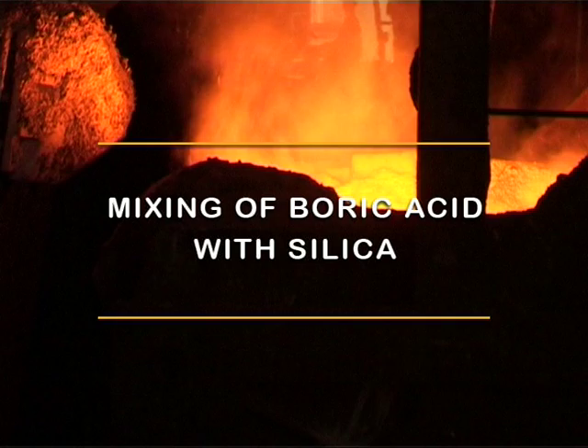Mixing of boric acid with silica. Can you comment on the use of boron oxide? Boron oxide is a replacement of boric acid, because as you know, boric acid contains nearly 50% of water, and during sintering you have to remove this moisture and this takes a long time.